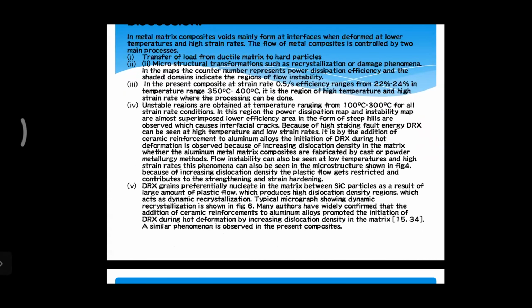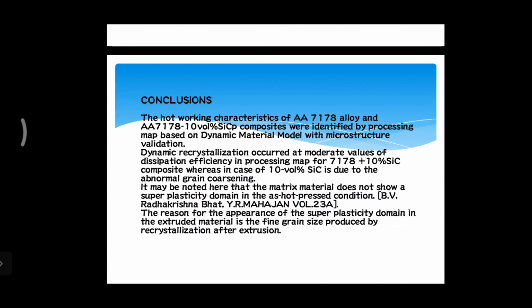So these conclusions: the efficiency at around 350 to 400 degrees centigrade for the composite material is 22 to 24%, and in the case of the alloy, it is more than that. So these are the interpretations, and the conclusion is that the hot working characteristics of AA7178 alloy and 10-weight% SiC composite were identified by the processing map. So we can say that on adding 10-weight% SiC, its strength, hardness, and flow stability are better than the alloy. So this is the validation with the dynamic material model, or we can say processing map.